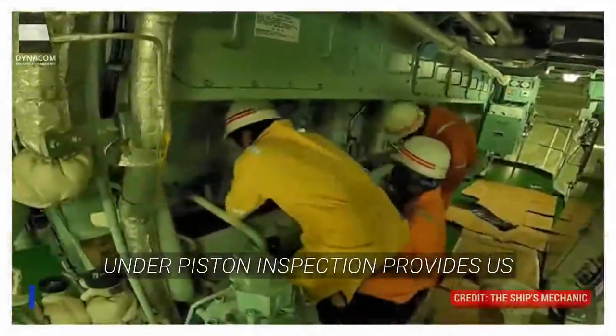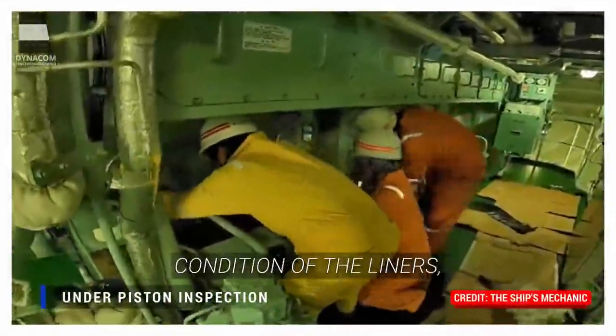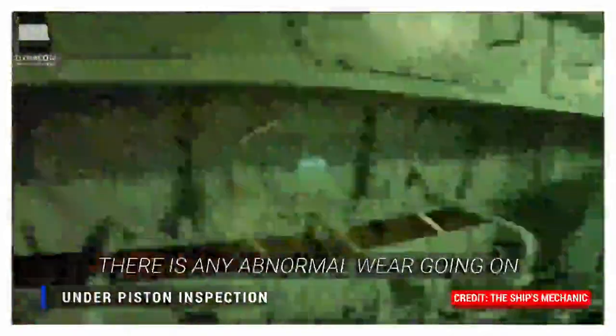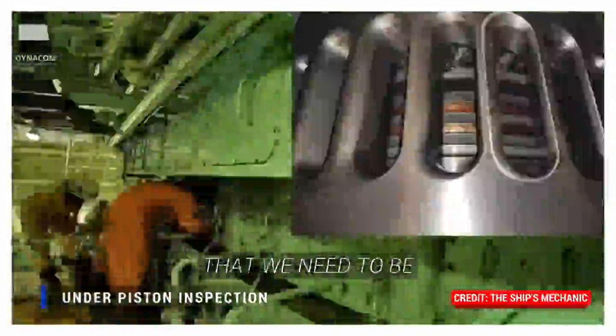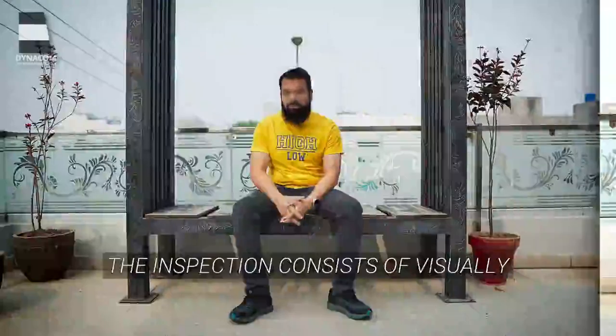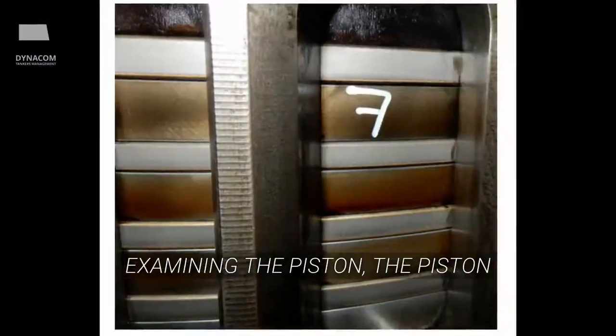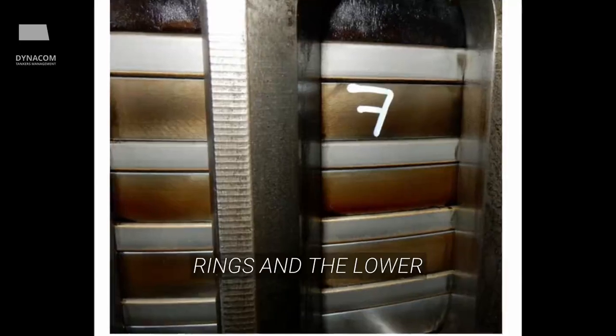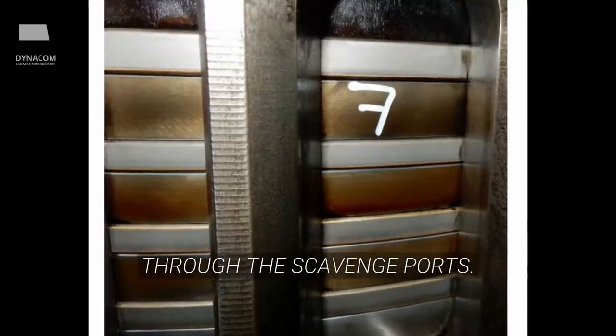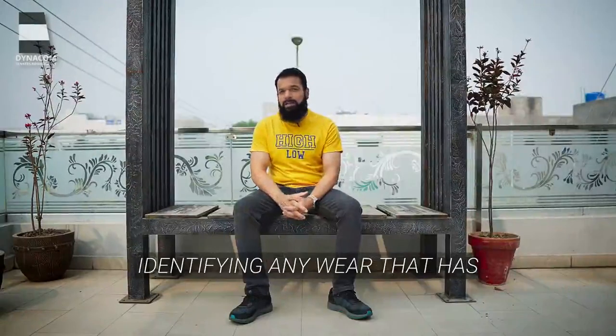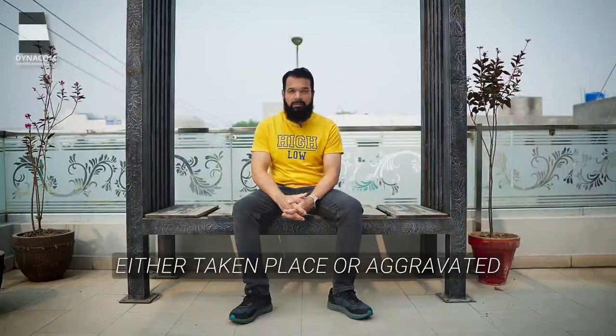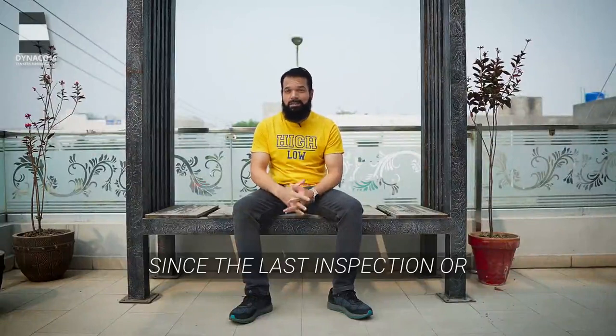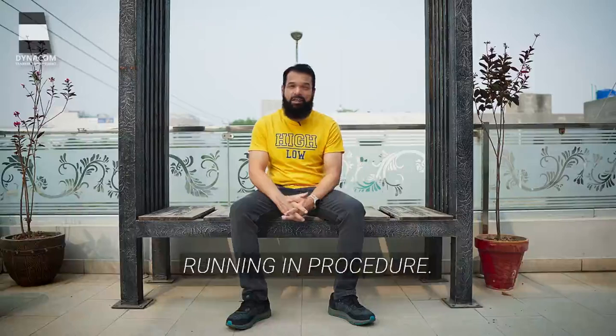Under piston inspection provides us careful information about the condition of the liners, pistons, piston rings and cylinders. This also helps us identify if there is any abnormal wear going on that we need to be particularly careful about. The inspection consists of visually examining the piston rings and the lower part of the cylinder liner directly through the scavenge ports. The focus needs to be on identifying any wear that has either taken place or aggravated since the last inspection or especially after the running-in procedure.